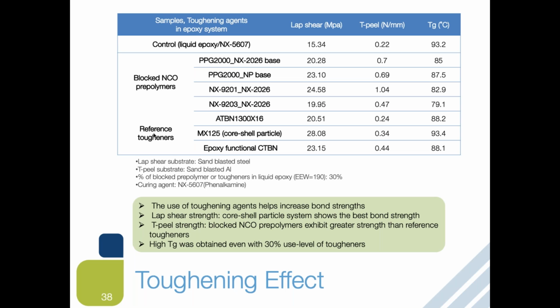So 70% of liquid epoxy, 30% of this ingredient, and then cured with NX-5607. What we have seen is, when it comes to lap shear, adding this blocked prepolymer and reference all improve the lap shear quite well. And from the data, core shell particle is the best, followed by some of the blocked pre-polymer.